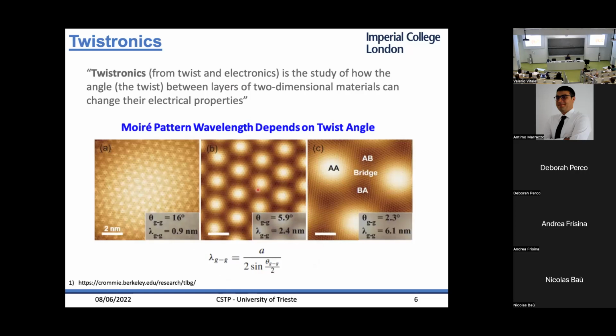As you can see, experimentalists have been working on this for a couple of years now, and they managed to actually produce devices with different 2D materials and different twist angles. This one in particular is for twisted bilayer graphene, which we'll talk about quite a lot. These are STM images in ultra-high vacuum, at ultra-low temperature. You can see how the Moiré pattern generates a Moiré potential that tends to localize states near the Fermi level. So these are actual STM images of these states near the Fermi level in twisted bilayer graphene.